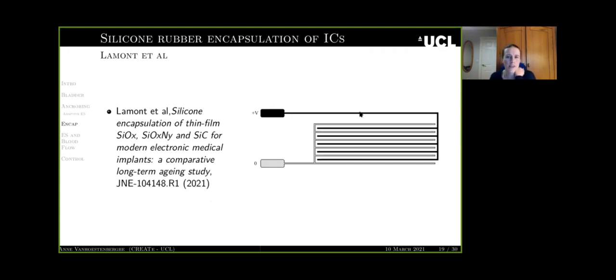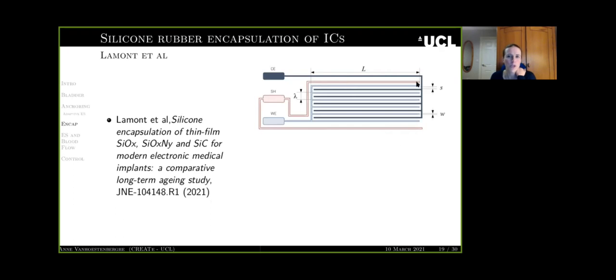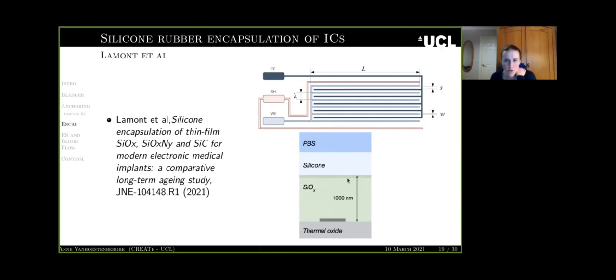And we compared the effects of these different passivation layers on top of a simple interdigitated structure, so a set of two electrodes. We have demonstrated that if you vary the different parameters of this set of electrodes, you can vary the depth of the sensor. Ignore the pink line here, this is a shield line that's used for other reasons. So this acts as a corrosion sensor, and we can vary precisely to sense any changes in this area right between the silicone rubber and the passivation layer, here presented as a silicon oxide layer. So we create our sensors to be very sensitive to about the 1000 nanometer region.